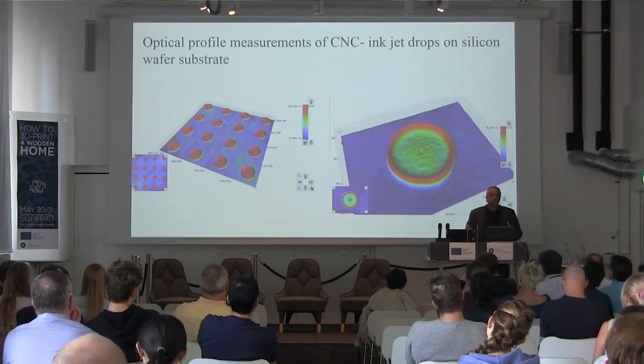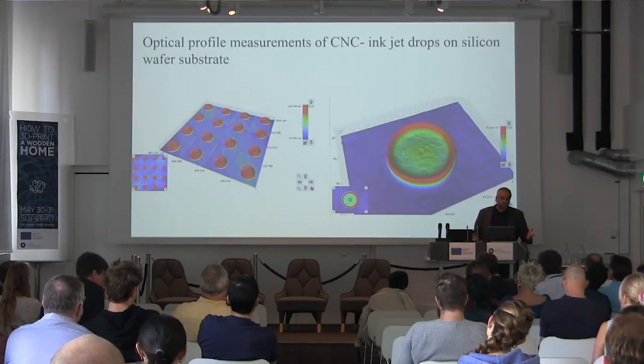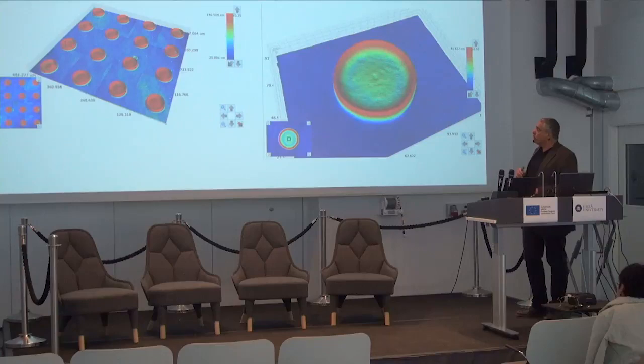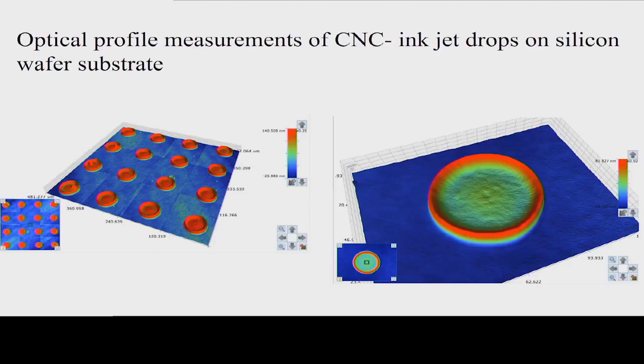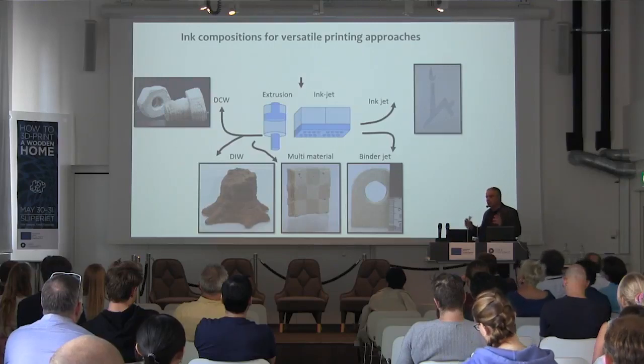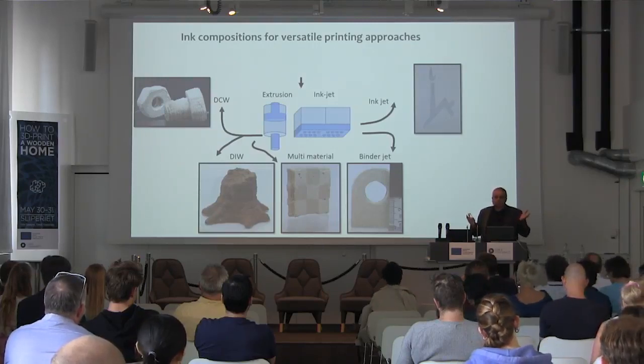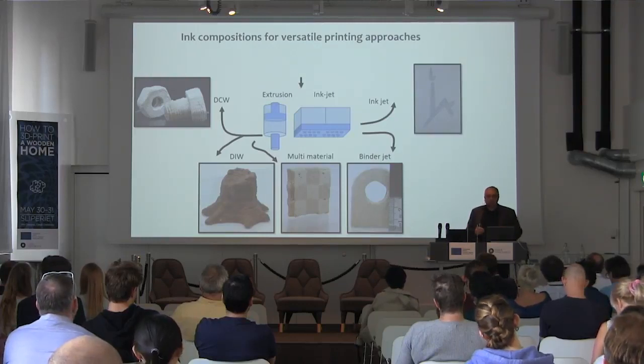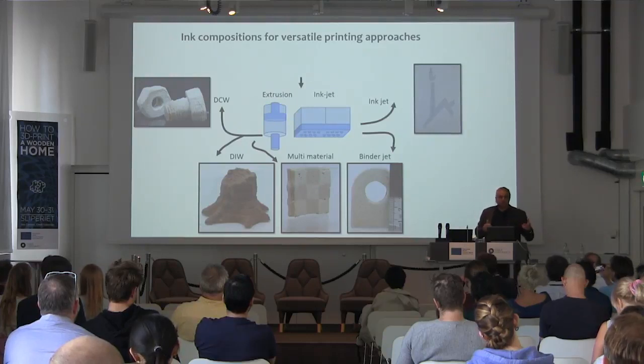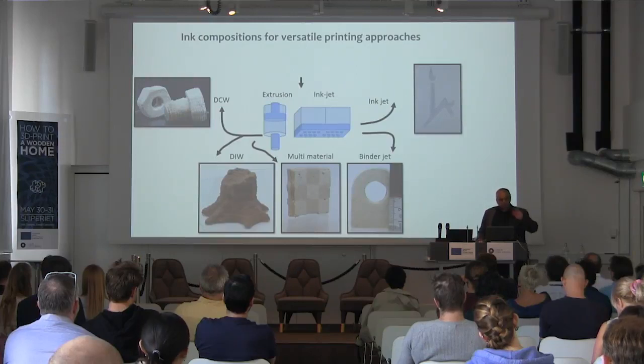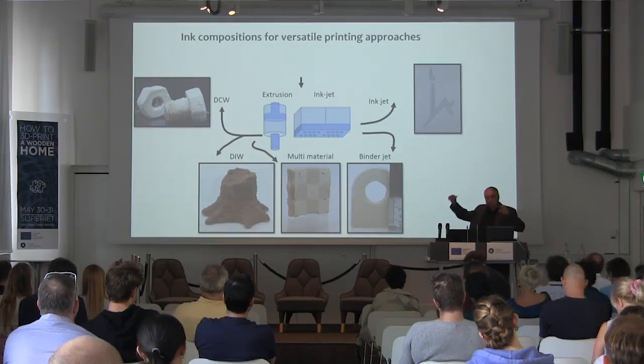Another thing that you can do with nanocellulose is jet printing. And here we've shown by optical profile measurements the reproducibility of these dots, and you can see here this ring, or coffee-ring-like effect, that is made. In the beginning that sounds like a bad thing, but actually it's a good thing because it enables us to print relatively light and strong material, and I'll get to that in a second. So you can see here different compositions of nanocellulose with other things, mainly simple sawdust from different sources, together with xyloglucan and some hemicellulose. All these materials were ink-jetted with no chemical binder. So everything here is made and extracted from wood.